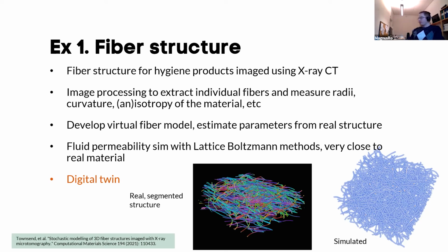To give you a couple of examples of concretely the kind of materials that we have analyzed, a couple of years ago, we had a collaboration with Essity, where we studied a fiber structure that they intend to use in different hygiene products. We did some imaging of the structure using X-ray computed tomography. So we got 3D data of the structure. We did basic image processing to extract the individual fibers. Once we have individual fibers, we can measure the radii. We can characterize what the curvature is, how much they bend or how straight they are.